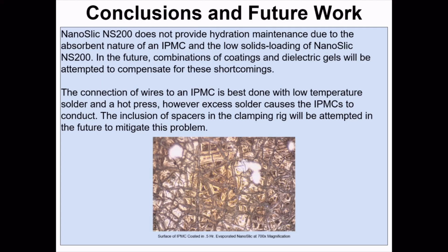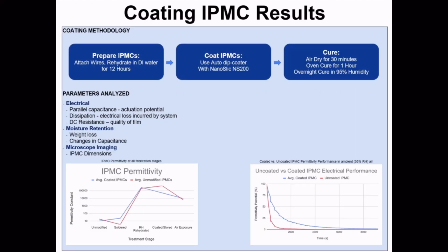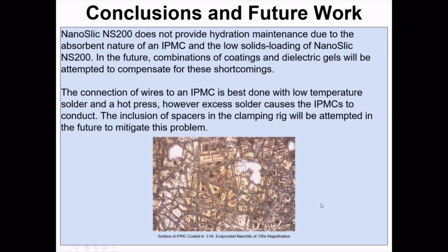So what did we take away from this? It's a good coating, but if you notice back here, it's not perfect. We're not getting exactly what we wanted. So why is this? NanoSlic is what's called a suspension. It's basically NanoSlic, the actual material, dispersed in some sort of liquid. So that's causing a lot of problems. In the future, maybe we can look at evaporating it in a different way or combining it with things called dielectric gels to hopefully fix this problem.